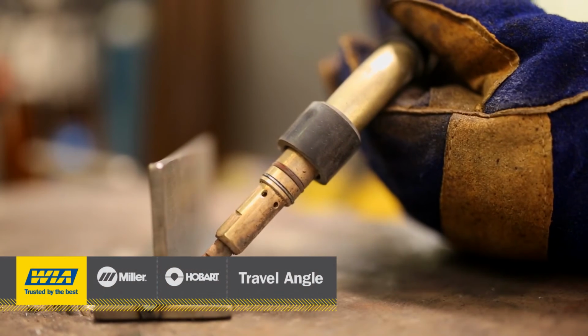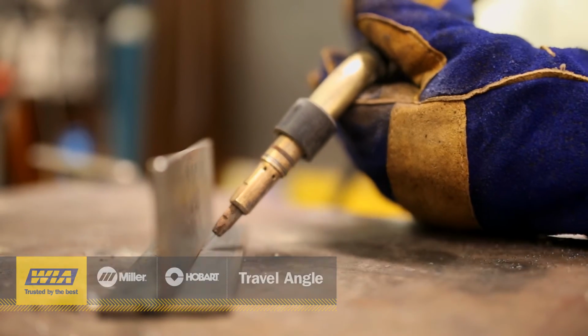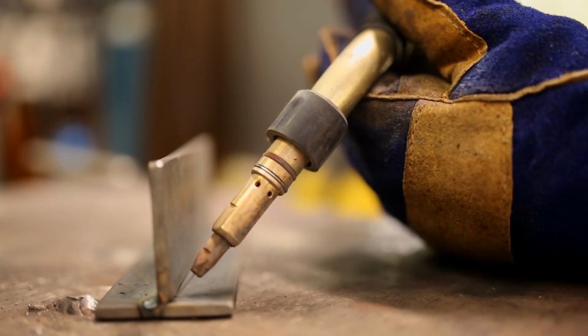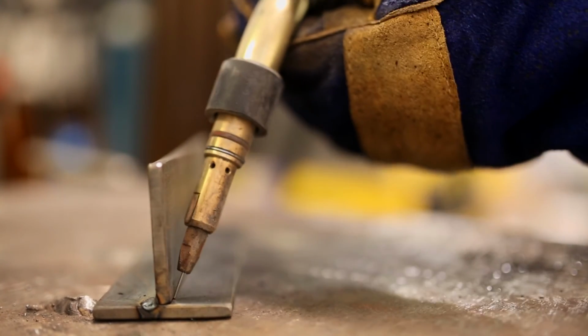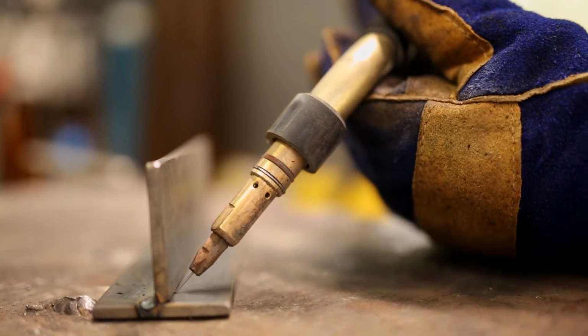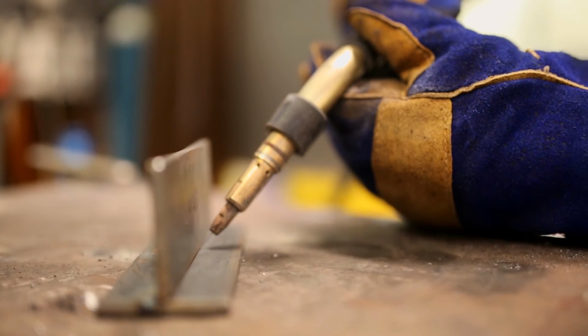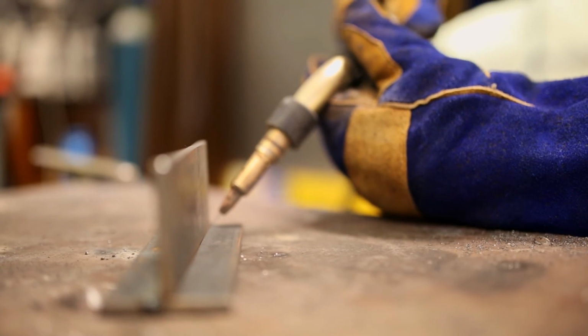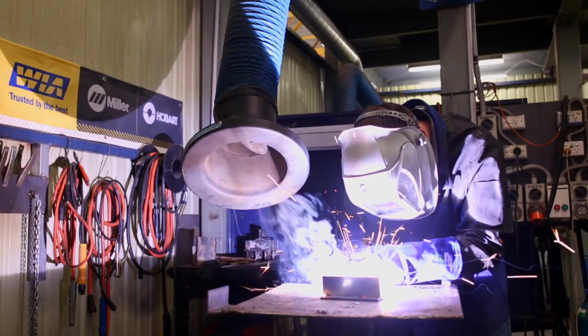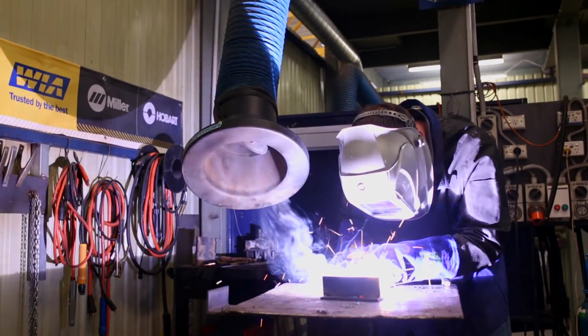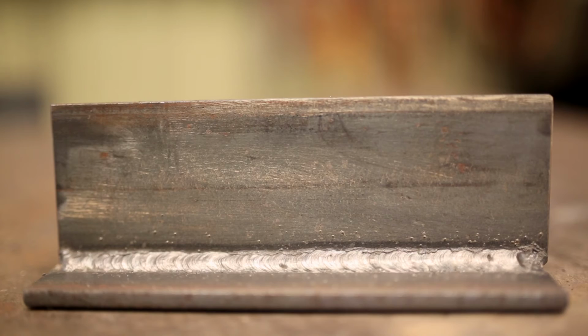Travel angle is defined as the angle relative to the gun in a perpendicular position within the plane of the weld joint. Normal welding conditions in all positions call for a travel angle of 5 to 15 degrees. Travel angles beyond 20 to 25 degrees can lead to more spatter, less penetration, and general arc instability.